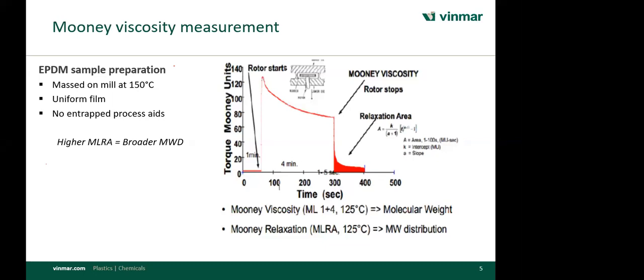So the important criterion is that you must run the mill at 150 degrees centigrade. That is very, very important since EPDM needs higher temperature. Second is a uniform film. Third, please ensure there is no entrapment of process oil coming from the mill or some wax-like substance present in the mill. And I can assure you, if you follow these standards and check the Mooney of the polymer, you will simply get a Xerox copy of your certificate of analysis at your laboratory.